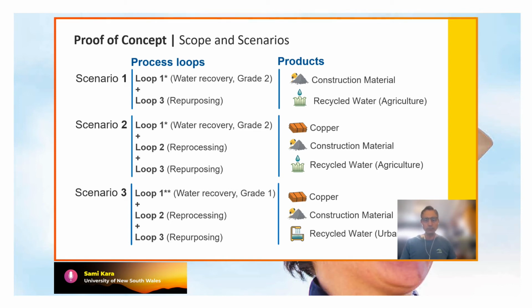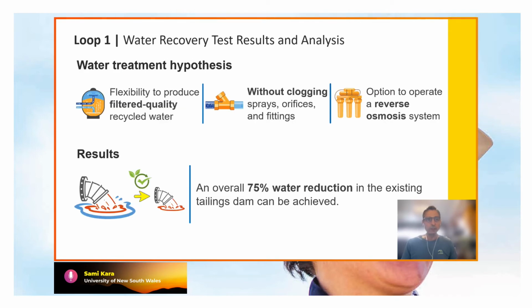consists of loop 1 and loop 3, and the final outcome is construction material and recycled water for agricultural use. Scenario 2 involves all 3 loops, and the final outcome of scenario 2 is copper, construction material and recycled water for agricultural use. And scenario 3 also involves all 3 loops, but the recovered water is further processed to grade 1, and the outcome is copper, construction material and recycled water for urban use. For loop 1, our results indicate that an overall 75% water reduction in the existing tailings dam can be achieved.